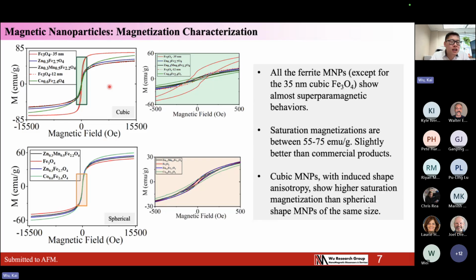The top panel shows the calibration of different cubic shape MNPs and spherical shape MNPs. If we cross compare these two different shapes, you can see that all the particles show a saturation magnetization around 55 to 75 emu per gram, which is better than the particles we can buy from companies. Secondly, we observe that cubic MNPs with induced shape anisotropy show slightly higher MS values compared to the spherical particles of the same size. You can compare these two figures here. All the particles are superparamagnetic, as we see from the magnetization curve here.